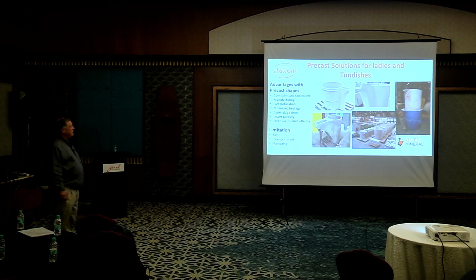The limitations are low resistance to chemical attack. It's very hard to get a really good density in a dry vibe in a ladle application, so you get a lot higher porosity than what you would in a low moisture castable. It's difficult to shave because it's not necessarily the strongest. Lower strength at operating temperatures, takes more time to install, and like I said before, higher porosity than what you typically find in low moisture, low cement castables.